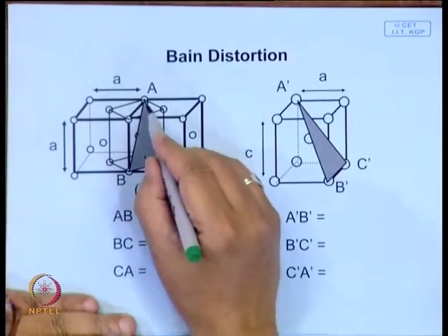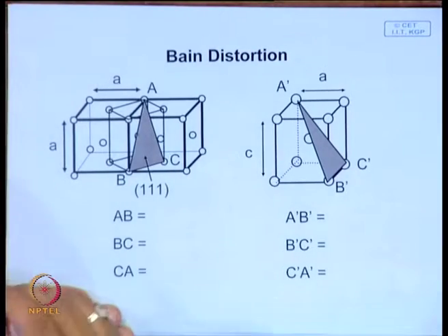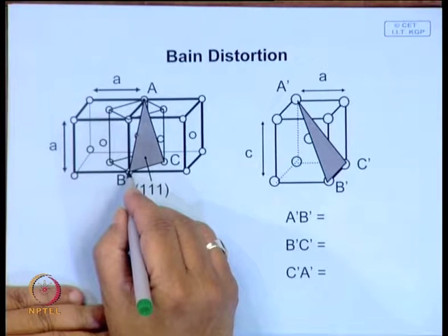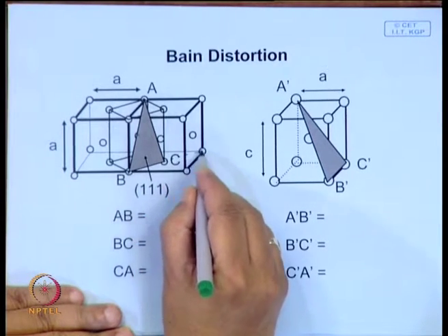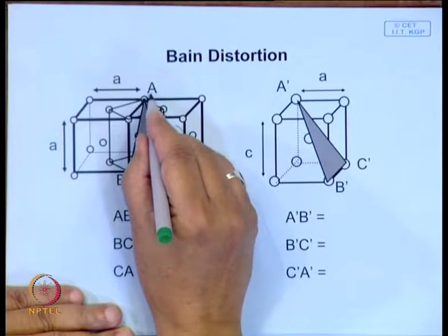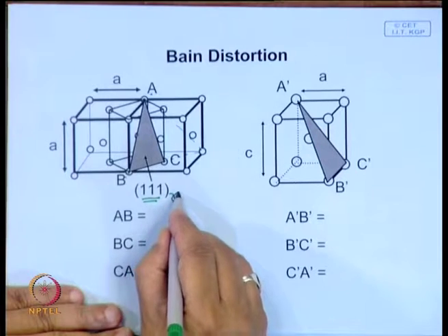Now, if this type of transformation takes place, then there are set crystallographic restrictions which must be followed. And look at this, this is shown in this next slide. Here, this is the cell in the previous diagram which gets converted into a body centered structure. Now, look at the correspondences of different planes and directions in this case. Try and find out what this plane is. It intersects here at unit distance, here at unit distance, and here, of course, you can extend it. So, this plane, named ABC, is actually a 1-1-1 plane, and this is a plane in the austenite lattice.